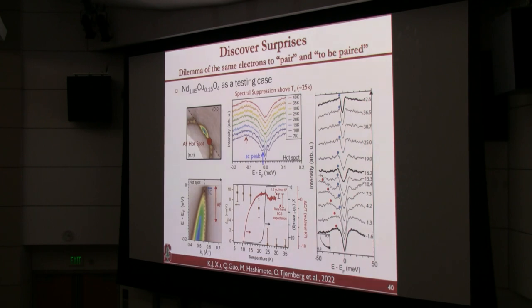So there are two things. One is superconductivity. The other is a broader, much larger range of spectral weight suppression. And just as a note, in this system you also see a very weak, very faint specific heat jump. This is probably the reason why no one has published the specific heat in this system. It's hard, which is a related subject. Now, if I go around here, you can see that the superconducting gap gets bigger and bigger, then gets smaller, changing non-monotonically.